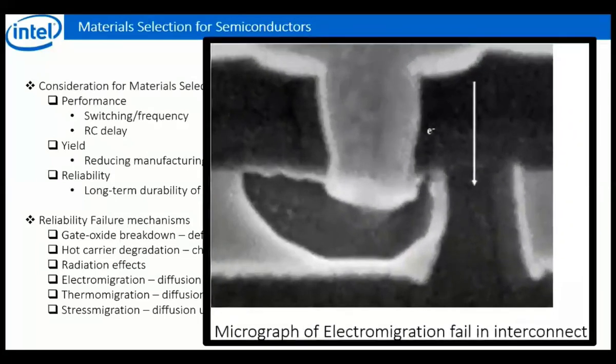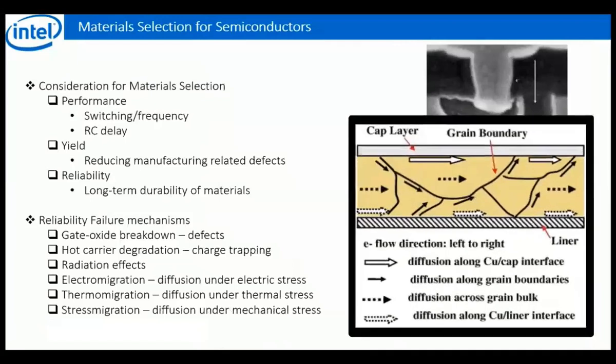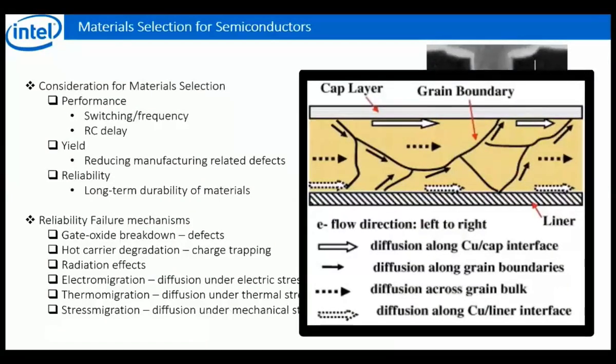So this is an electron micrograph of a hole inside a circuit. And you can see all the copper has been taken out through electromigration. And so this can happen in various ways. Diffusion can happen through the top surface. It can happen through grain boundaries. It can happen through sidewalls.